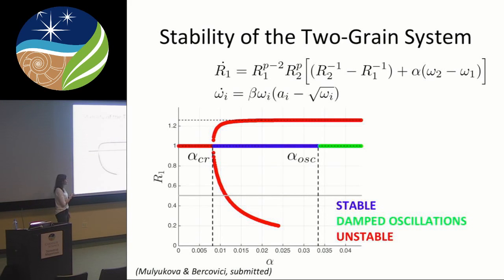If you crank up your alpha even higher, how much you allow for the dislocations to matter, you can reach a set of solutions where mathematically there is an emergence of imaginary components to your solutions, which means that you now allow for oscillations to exist in the system. In simple terms, this emerges because the grain growth is governed by diffusion scale processes. So this is diffusion of atoms across the boundary. Dislocations act on their own specific time scale of migration and velocity of large-scale defects. So because there is competition between two different time scales, this allows for a possibility of oscillations within the system.